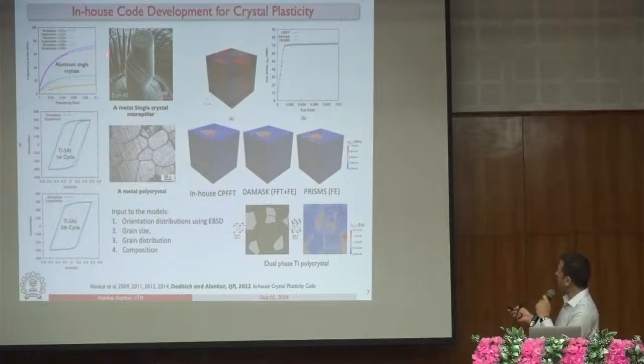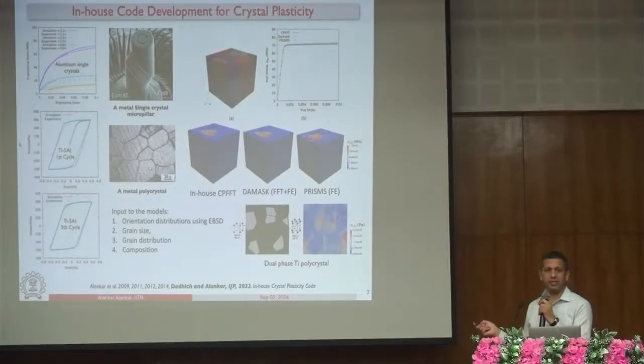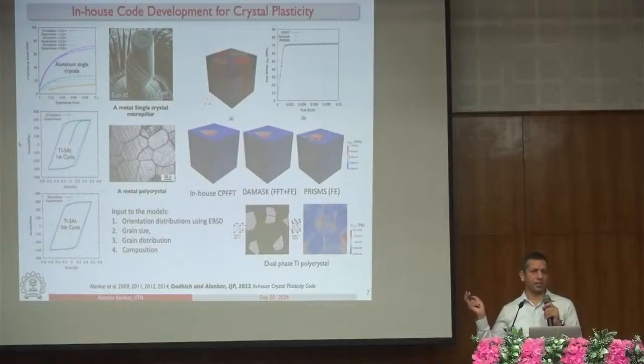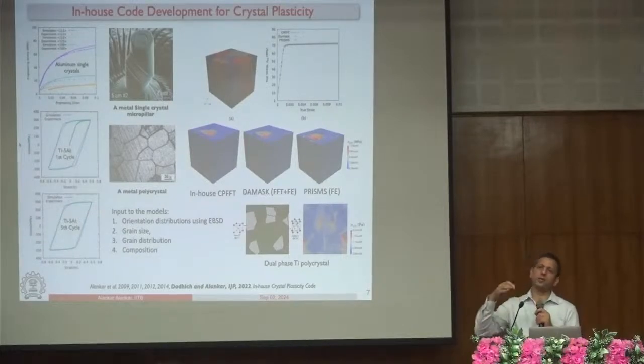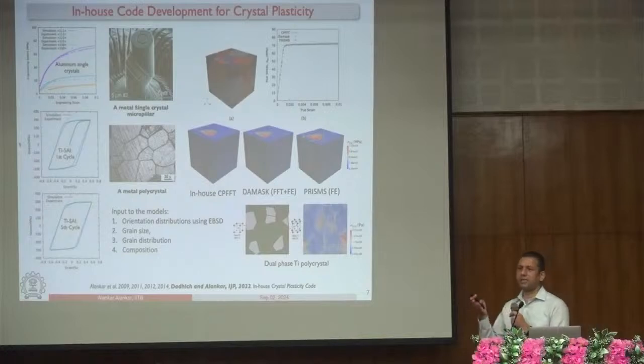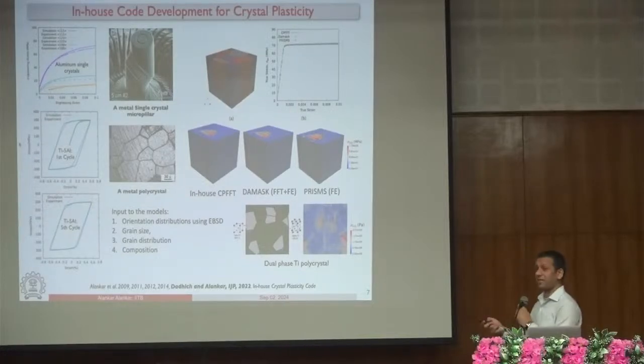What you see here is a micro pillar of a metal. This is a single crystal. Essentially, there is no grain boundary. If you compress it, there will be deformation. And in metals there are slip planes and directions, and because of those, the plasticity happens along certain planes. It is constrained on those planes, and the shear will happen along certain directions. Right, so you see these slip steps, right? It is important to understand that, because as the loading condition changes, as the temperature changes, the amount of slip, direction of slip, and all this will change, and it will overall affect properties like yield strength or UTS, even the fracture, right?